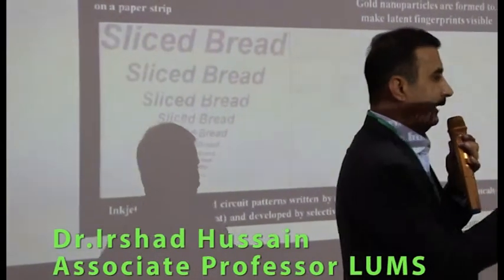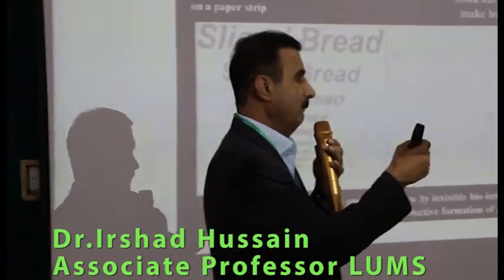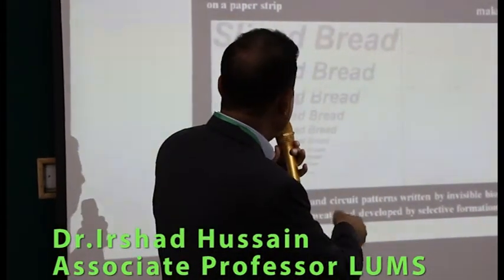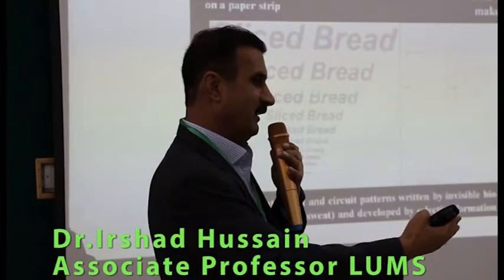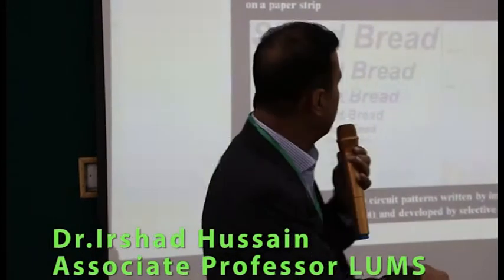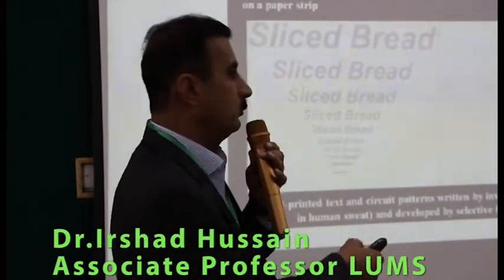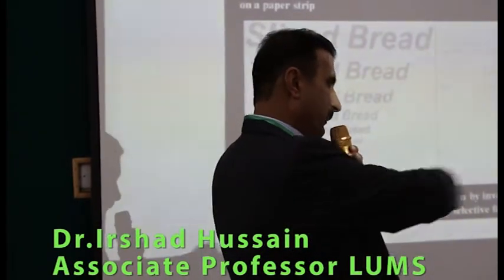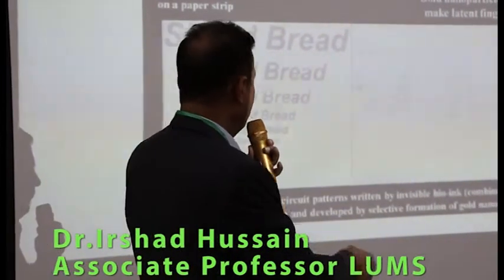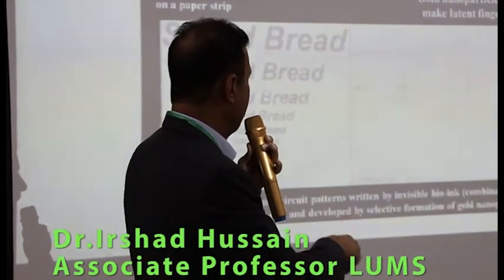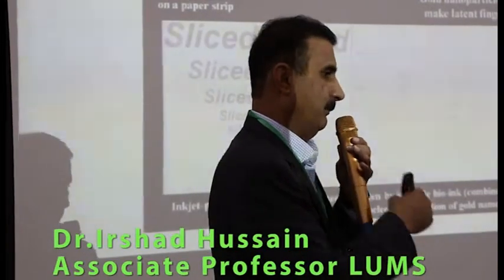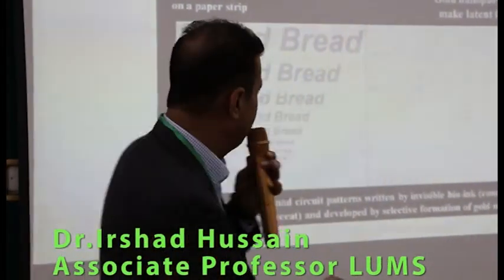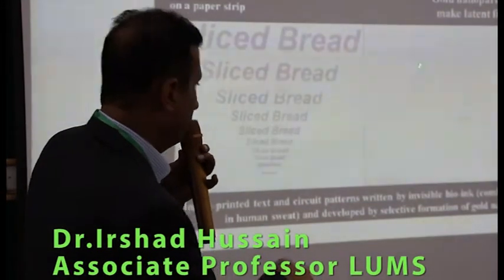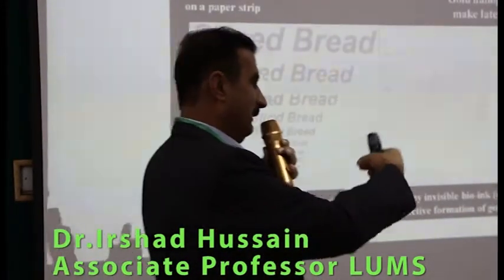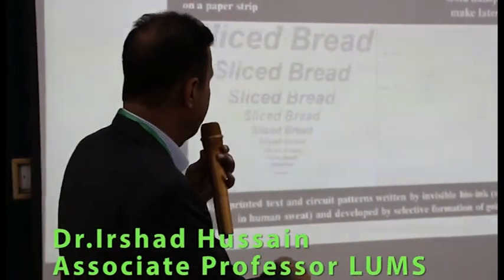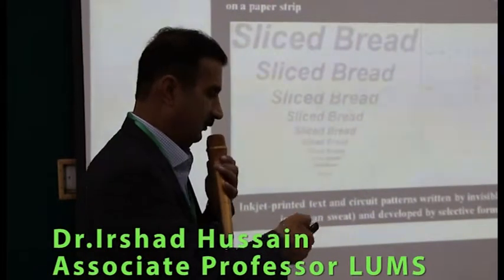And then we made bioink. Using that biosurfactant, we developed bioink to print these text patterns and circuit patterns on different substrates, plastic and other materials. So initially these were not visible, but you can produce gold nanoparticles specifically on those printings, which was done by inkjet printing, and you can develop these type of things. So we actually were targeting that we may be able to develop some flexible electronic materials, but unfortunately in this case, when we observed in the electron microscope, still there was a huge gap between particles, so they were not conductive in nature. So we are still trying to make these conductive